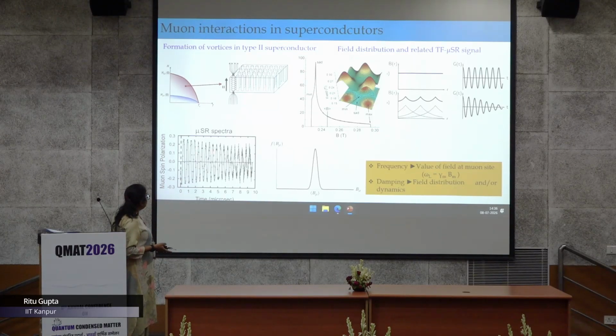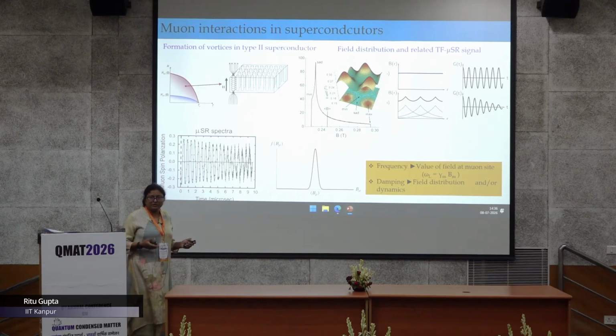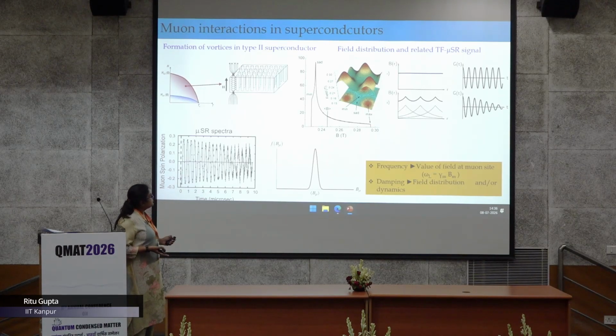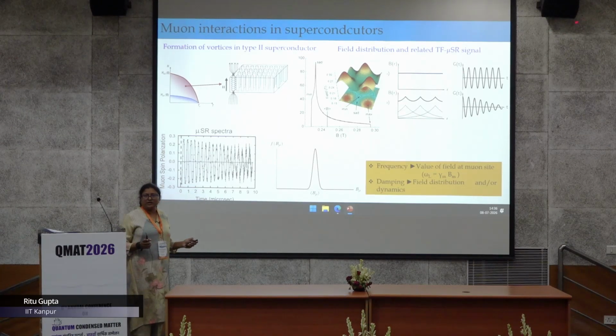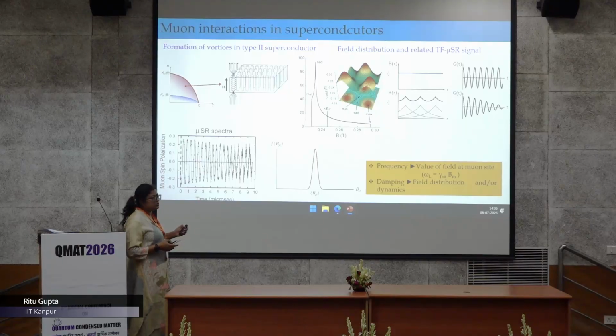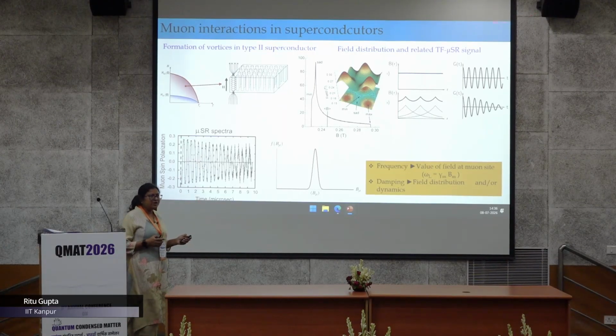But if it is in the vortex state, as I explained, the muon will see three different fields. Then, of course, if your crystal is very pure, with a very high RRR value, you should see this asymmetric line shape. But if you have a polycrystalline sample or not a very good single crystal, then of course this asymmetric line shape effect will be masked, and you will see broadening.